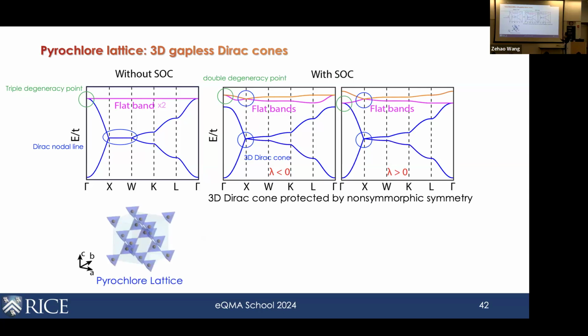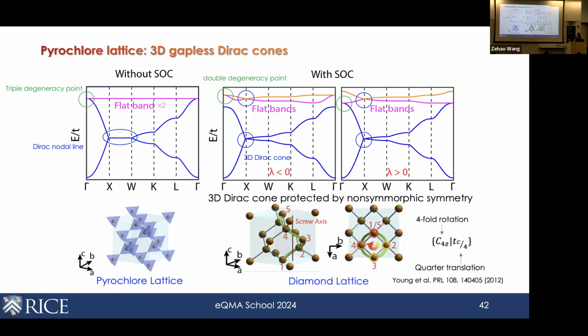The easiest way to draw this, I guess, is to picture the pyrochlore lattice. If you take the center of each tetrahedron, that gives you this diamond lattice, and it was actually predicted a decade ago that a diamond lattice has the screw axis. So non-symmorphic symmetry means you have a combination of a translation and either a rotation or a glide mirror symmetry, right? Here, in the diamond lattice, as you can see, traced out by this green stuff, there's a screw axis, and there is a symmetry operation.